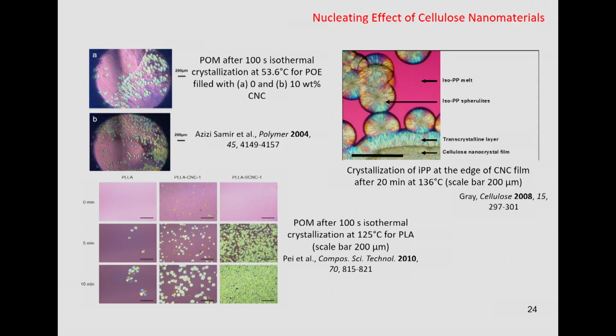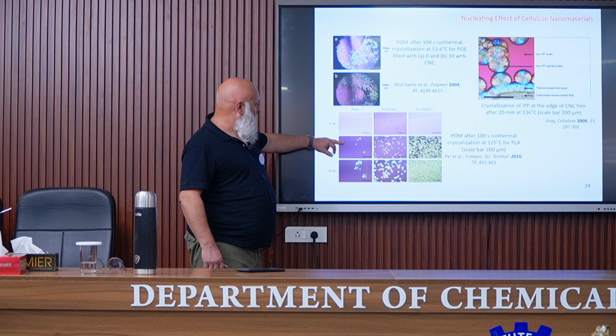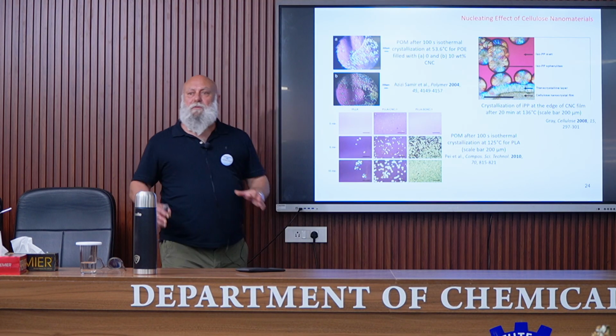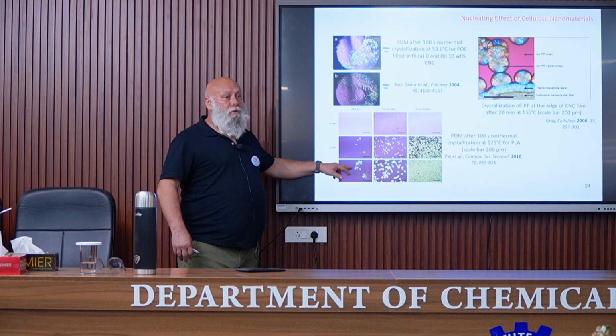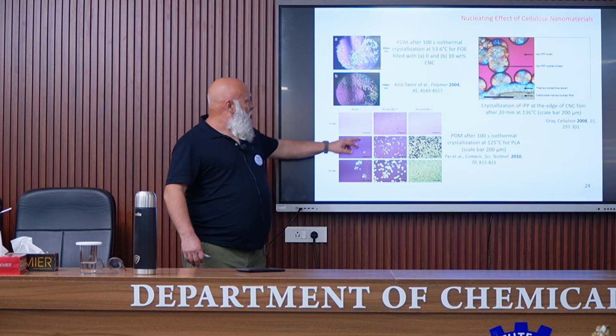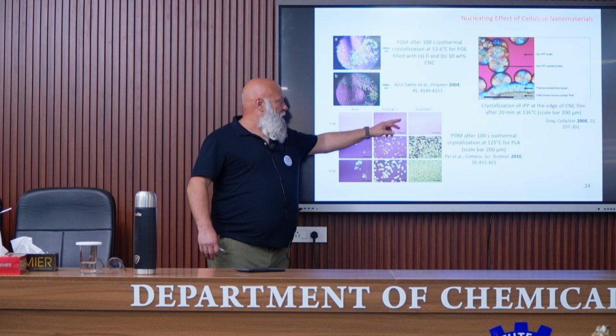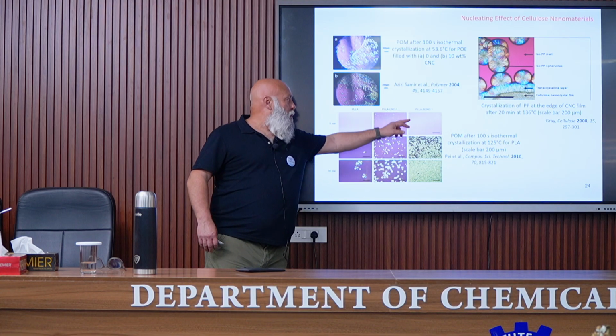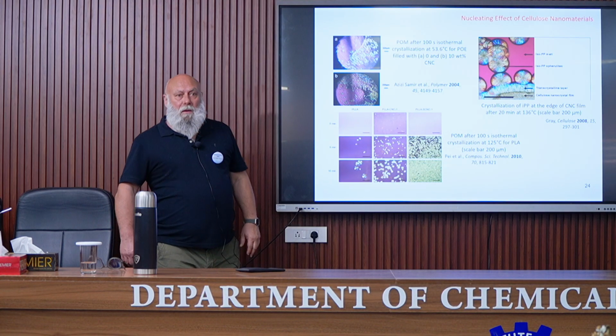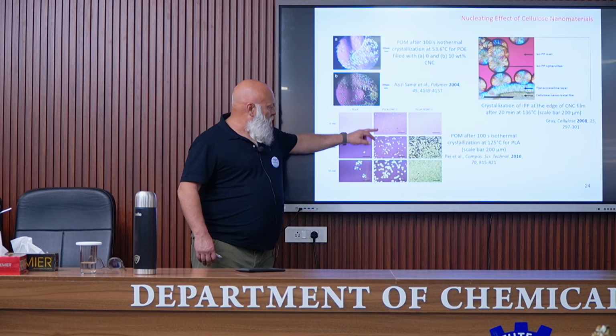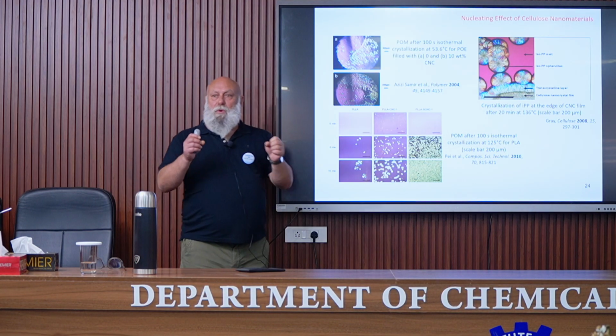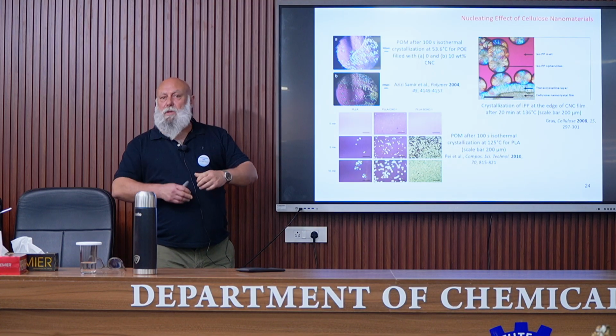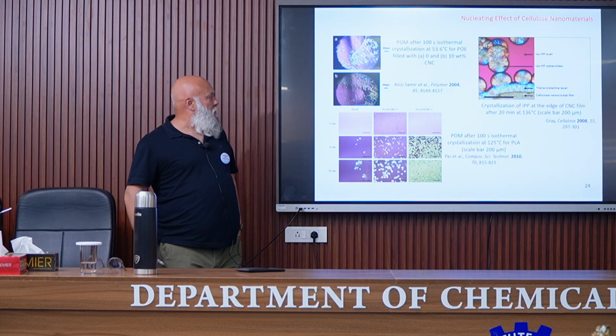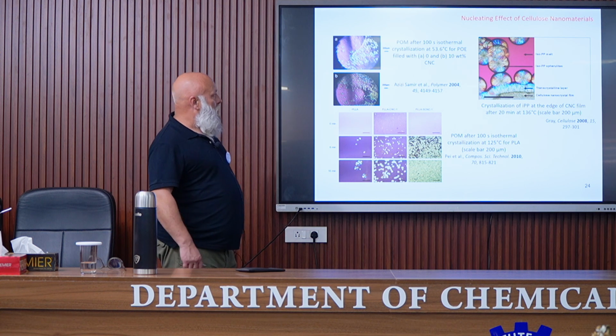This is similar with PLA, pure PLA, so crystallization was performed at 125 degrees Celsius. Pure PLA, we have the formation of spherulites. You can see few spherulites, but the size is big. When adding 1% modified nanocrystals, using a silane in this case, you can see that the crystals are much smaller, but there are more crystals, meaning that nucleation is favorable.